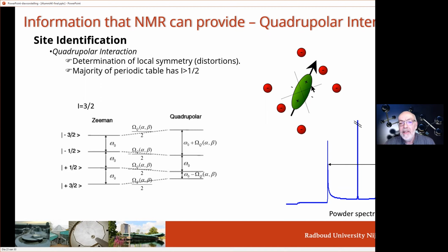On top of that, we call them quadrupolar nuclei, this nucleus is not a little sphere. It can be an ellipsoid or a pancake. And that means, depending on the charges that surround the nucleus, different orientations of the nucleus will be energetically more or less favorable. And that causes all these energy levels to shift. And as a result, from a single site, we get a spectrum with multiple features like this.